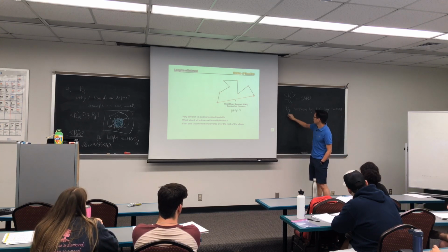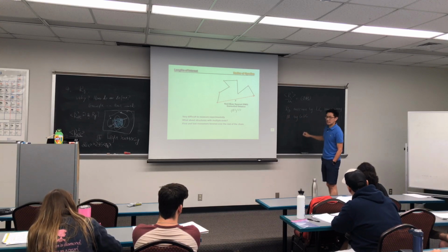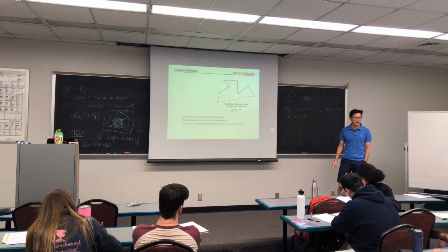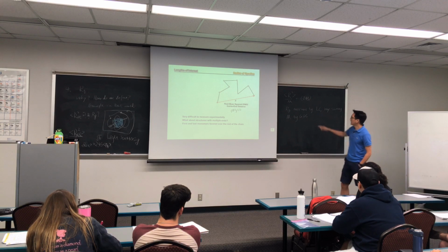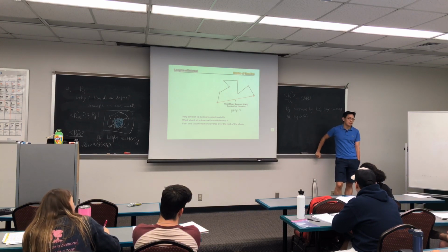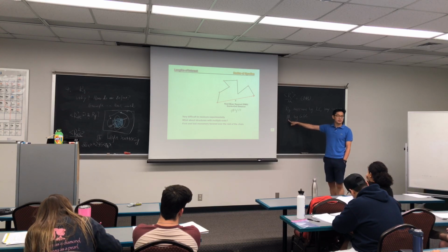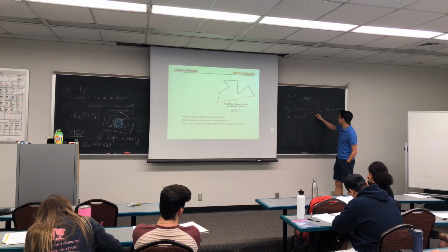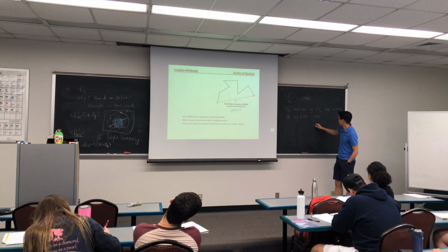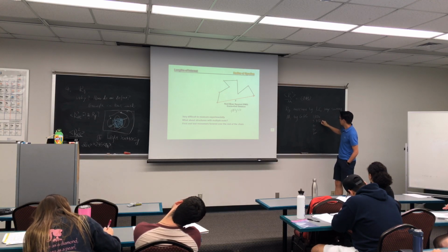Then you can measure molecular weight by GPC, a technique that will tell you how big your molecules are in terms of molecular weight. So combining both, you should be able to construct that table by yourself. You can synthesize your polymers with a known molecular weight, like 1 kilodalton, 5, 10, 30, 100, let's say.